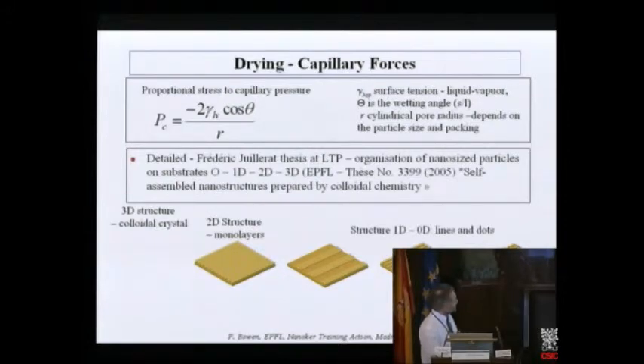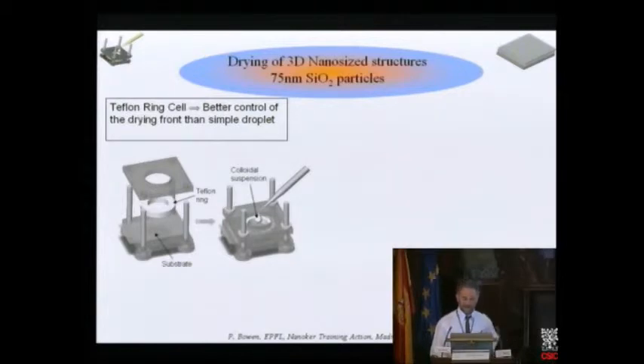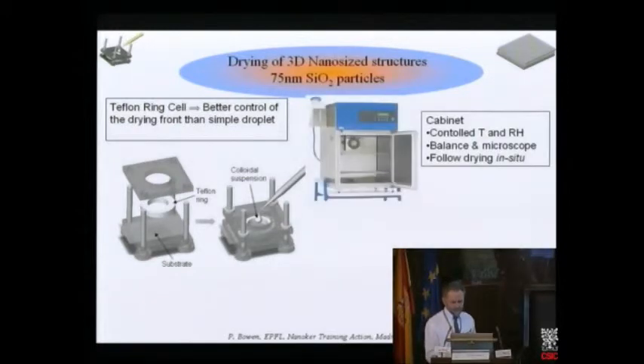So Frédéric Juillerat, in his thesis, looked at forming different types of colloidal nanostructures and looked at the drying in detail. So here we've got a Teflon ring. We put our suspension in. So these are 75 nanometer silica spheres, relatively narrow size distribution. And then we let it dry. So we control the drying in a control cabinet. We control temperature, relative humidity. We have a balance and a microscope, so we can follow the drying in situ.